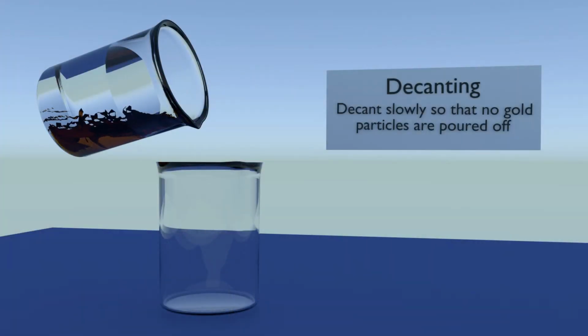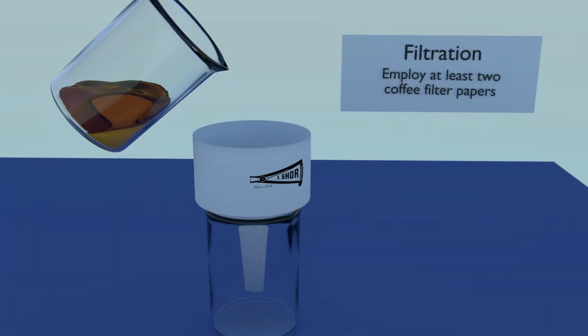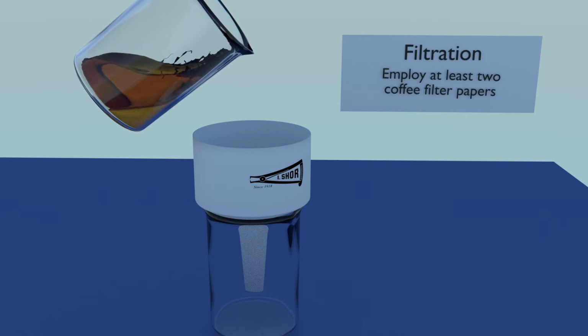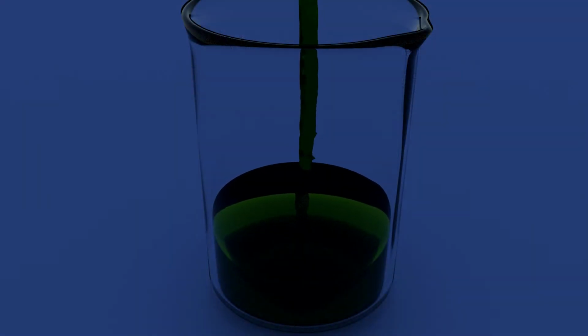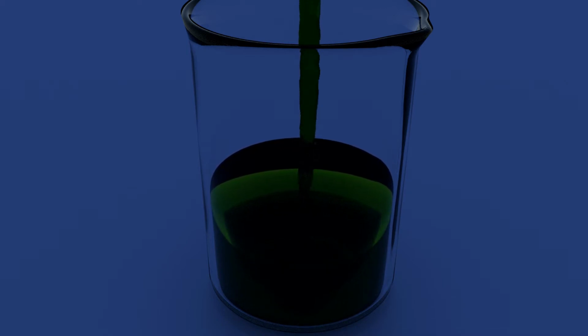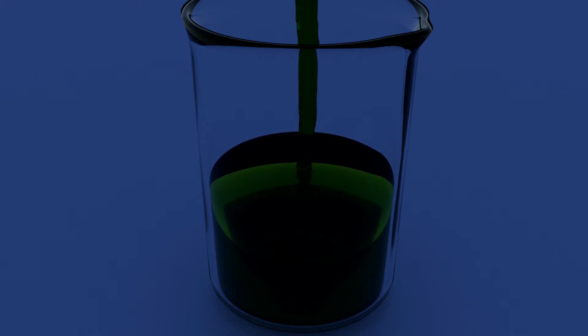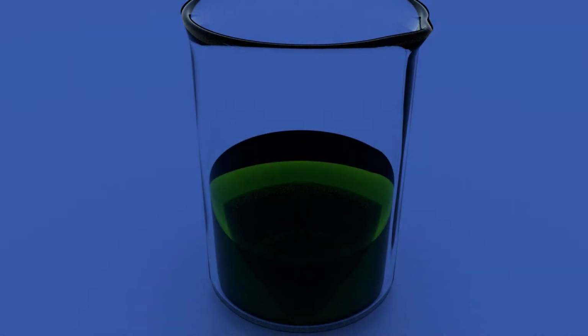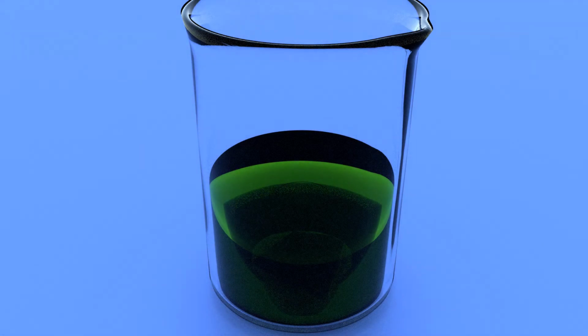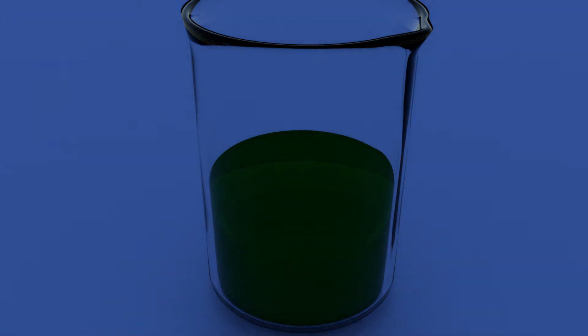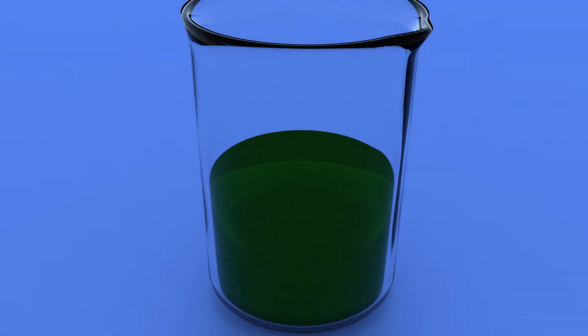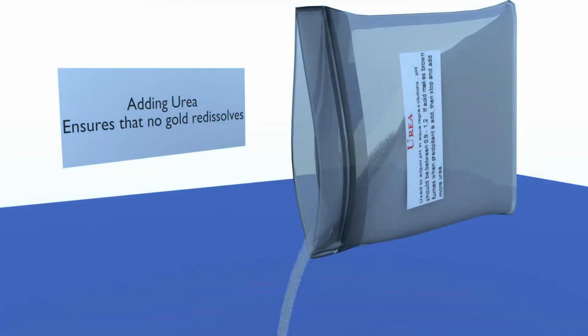Decanting is carefully pouring the solution off the top till the beaker is empty of solution. If you prefer to filter, use a Buchner filter funnel and use 2 coffee filters. After filtering or decanting, the solution should be clear of all solids, including particles. The solution may be very, very dark, and that's fine. However, it should not be even a little cloudy or murky. If you see any cloudiness or murkiness, it means that there are particles floating in solution, and you should filter or decant again.